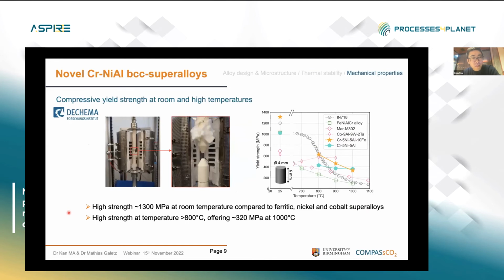So finally, we are also interested in the strength of this material at high temperature, and we use the high temperature compression rig developed in Matthias' group in Germany. We compress this cylinder to get a stress-strain curve and determine the yield strength of the material at different temperatures. Here we show some results at room temperature and at temperatures higher than 800 degrees. You can see the quaternary chromium BCC superalloy has high strength at both room temperature and temperatures higher than 800 degrees, which is the temperature for the end application.